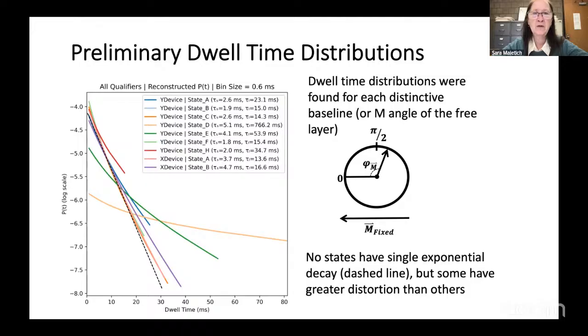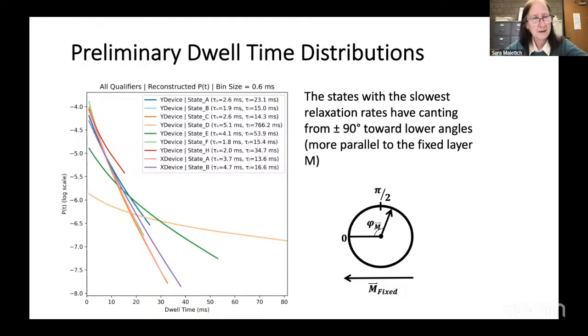For example, if you wanted to use short-term memory for voice recognition, speech recognition. So in this case, we look at the relative angle compared to the fixed layer fringe field. And these really slow relaxation states are always less than plus or minus 90 degrees. More than 90 degrees, those are very rapidly decaying. So there's clues to what is happening, but there's also a lot of additional information here that we want to understand to engineer our spin ice.